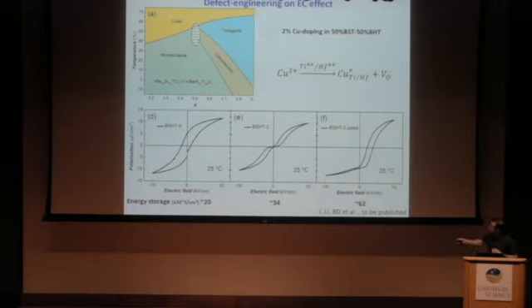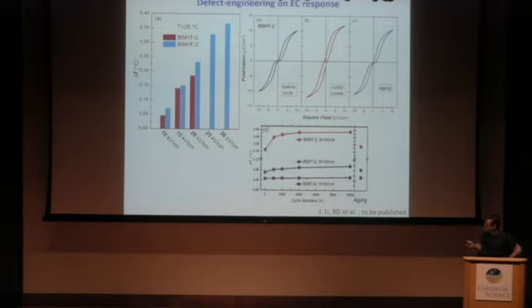Okay? So this kind of system is very interesting. And what you can see also is that by playing with the disorder, for instance, you can also enhance the energy storage, which corresponds to the area, which is exactly here. So you see, in that case, the area is much bigger. So defect is a very, very interesting way to design some peculiar properties. So let me show just some results with this defect engineering. First, once you add the copper, you can apply much higher electric field. And the higher the electric field is, the higher delta T is. Okay, so this is already something.